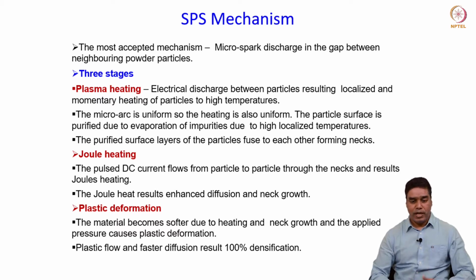Okay, and as I said, the heating here basically takes place by the Joule heating mechanism, where a pulsed DC current flows from particle to particle through the necks and results in heating. Okay, and this kind of heating also results in enhanced diffusion and neck growth, right? So that ultimately leads to a faster densification in this process compared to the conventional sintering processes.